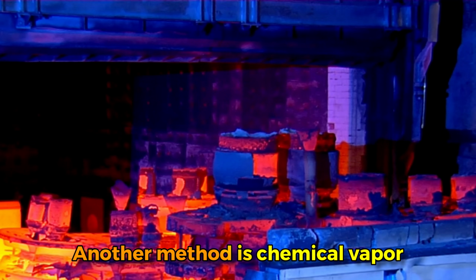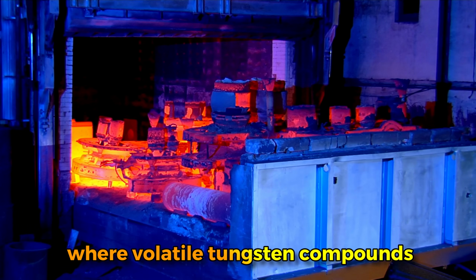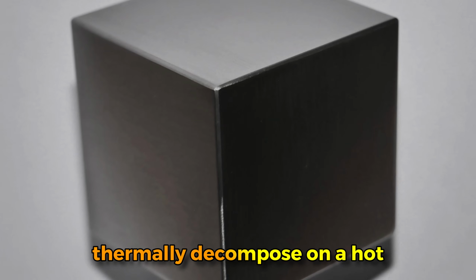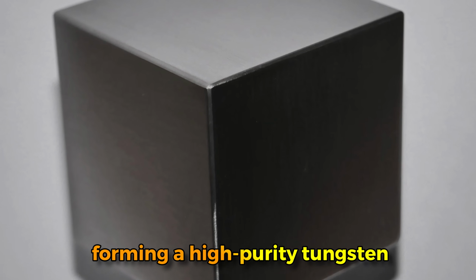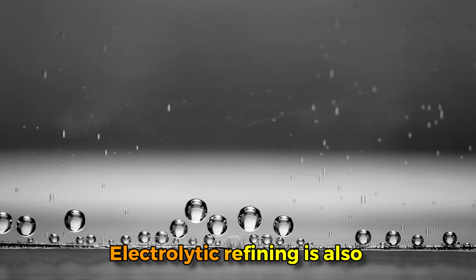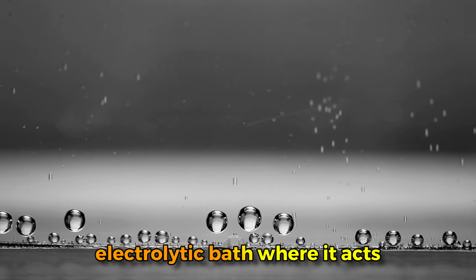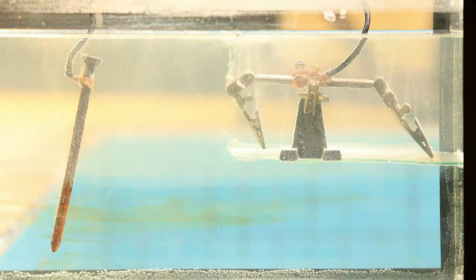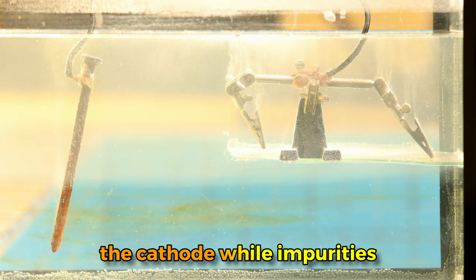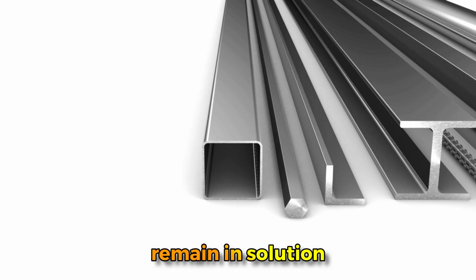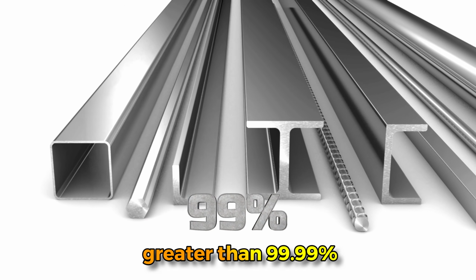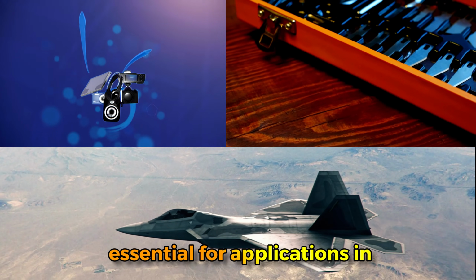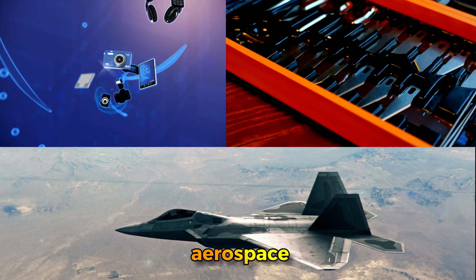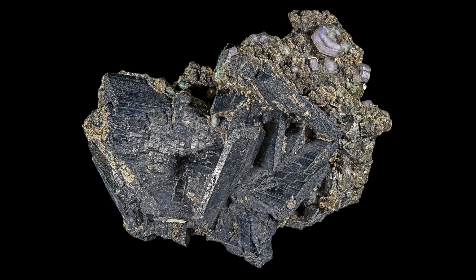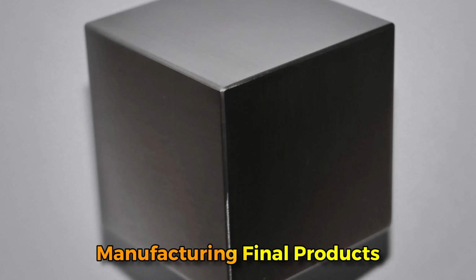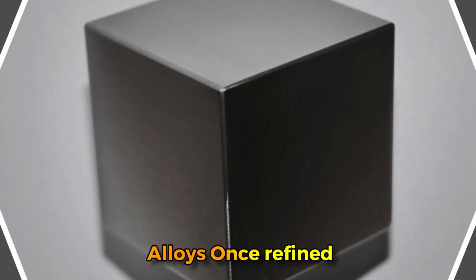Another method is chemical vapor deposition, CVD, where volatile tungsten compounds thermally decompose on a hot substrate, forming a high-purity tungsten layer. Electrolytic refining is also used, immersing the tungsten in an electrolytic bath where it acts as an anode. The pure metal is deposited on the cathode while impurities remain in solution. Refined tungsten reaches purities greater than 99.99%, essential for applications in electronics, aerospace, and precision tools. Step 7. Manufacturing final products, cutting tools, filaments, alloys.